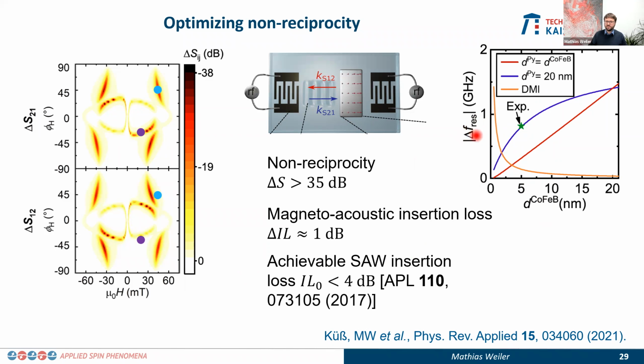And in total, what's nice about this is that optimizing the non-reciprocity using these dipolar interactions does not require you to make the films extremely thin. Whereas you need to make the films extremely thin if you want to optimize non-reciprocity with DMI, but that would also increase the linewidths. So it will be challenging to obtain a large non-reciprocity with DMI alone.